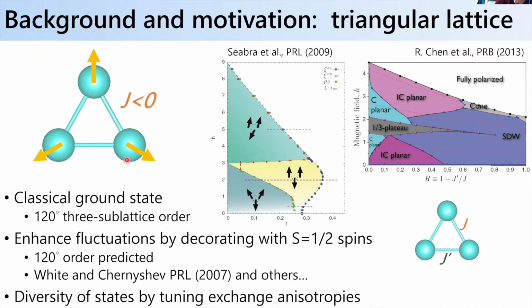And even this classical picture has very interesting behavior. It means if you were to change magnetic field, you can drive what's known as a 1/3 magnetization plateau state, or the up-up-down state, where you get 2 spins on one sublattice that point in one given direction, and the third points anti-parallel to those 2, and that's a fluctuation-driven state. But then you can also add complexity by changing out of the classical limit. You can start to think about decorating this lattice with quantum spins. So, for instance, spin 1/2 moments, where you can really enhance quantum fluctuations. And that was an outstanding question for a long period of time. But I think the picture now is that indeed 120-degree order is also predicted in the spin 1/2 limit.